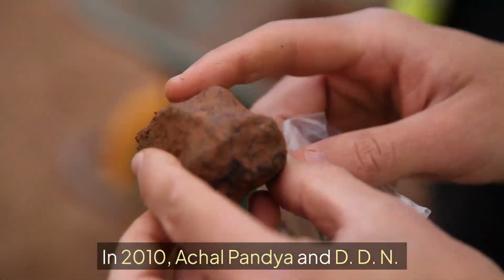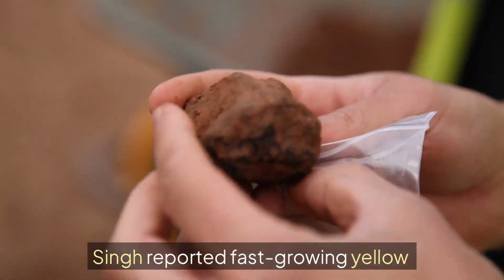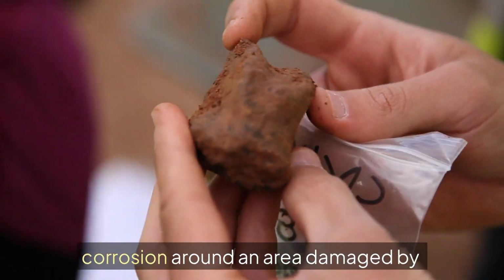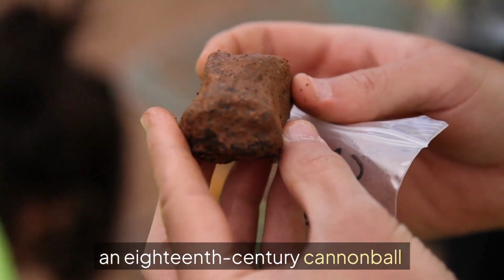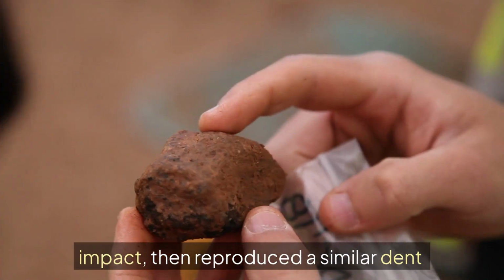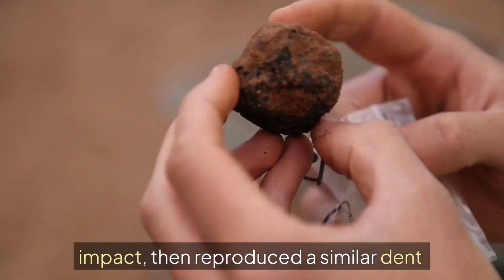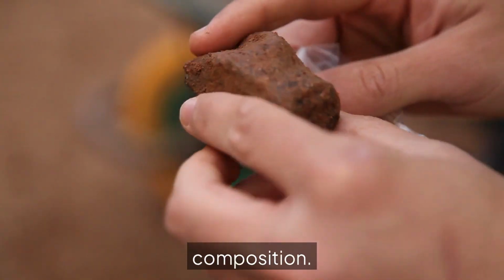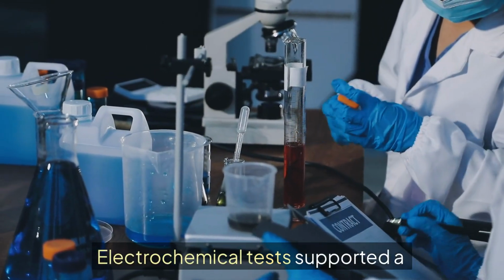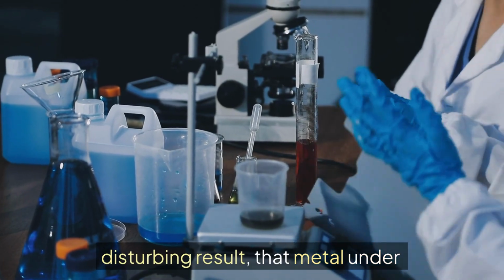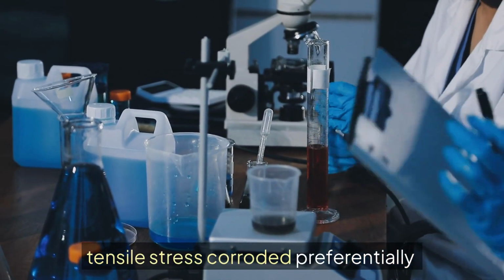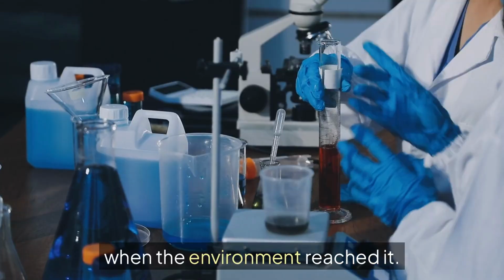In 2010, Achal Pandya and D.D.N. Singh reported fast-growing yellow corrosion around an area damaged by an 18th century cannonball impact, then reproduced a similar dent in iron with a comparable composition. Electrochemical tests supported a disturbing result. That metal under tensile stress corroded preferentially when the environment reached it. The monument still needs monitoring and conservation.